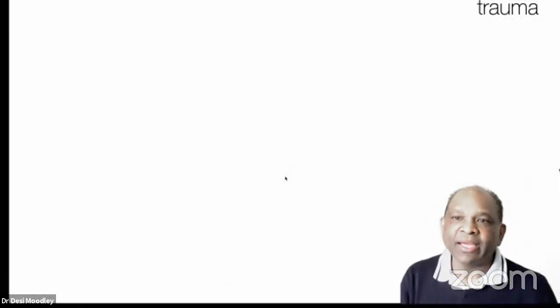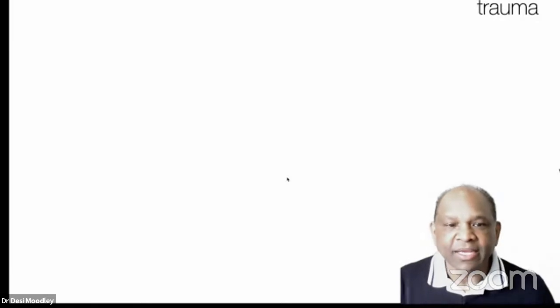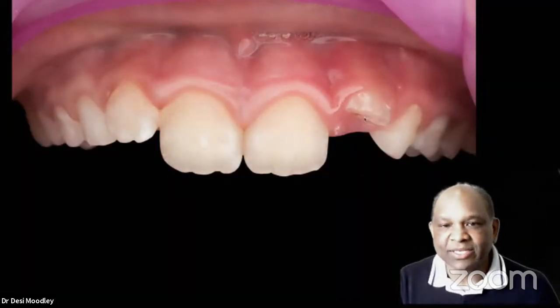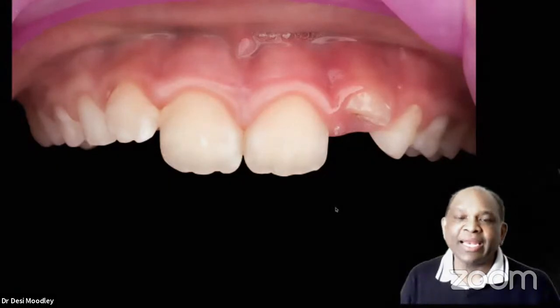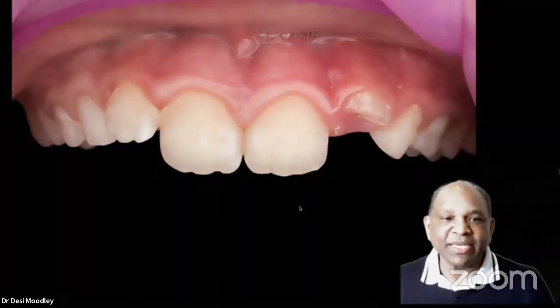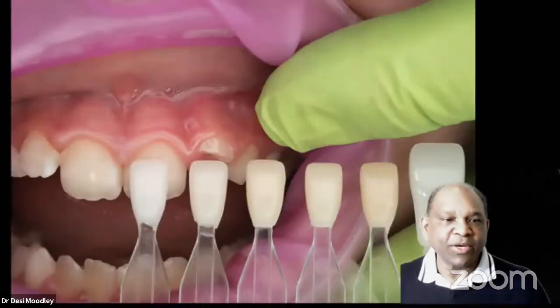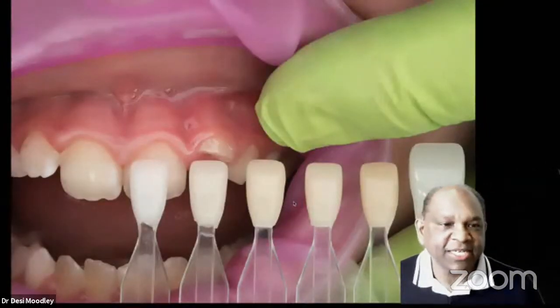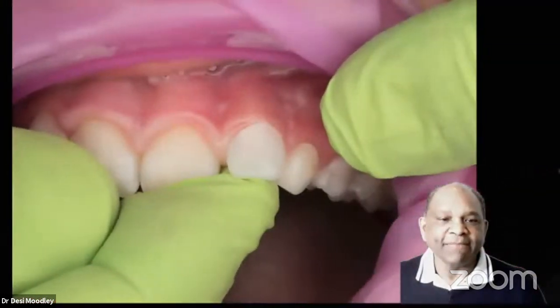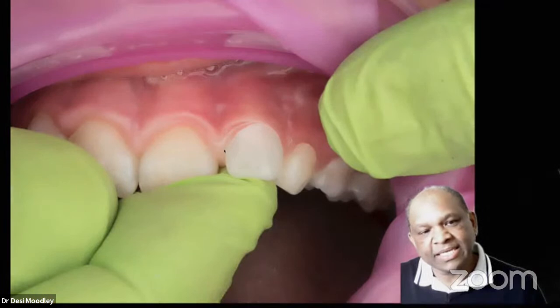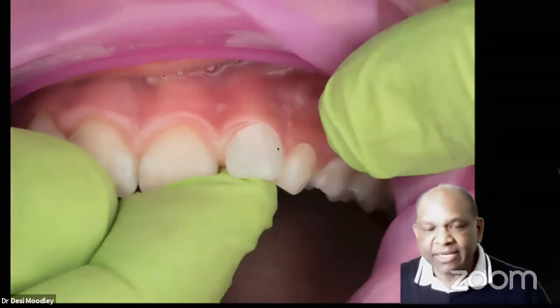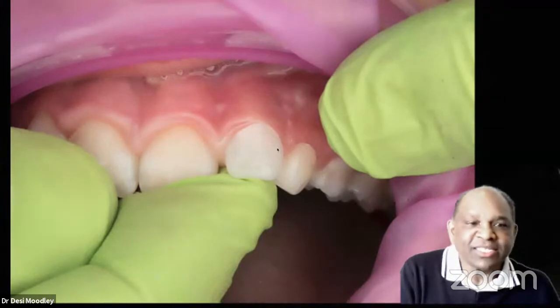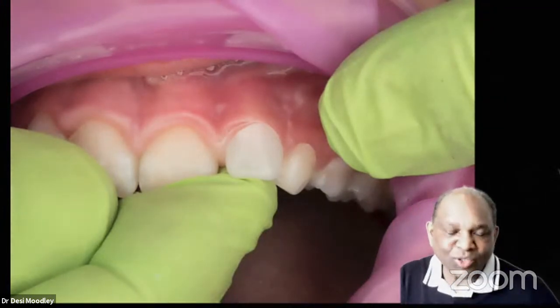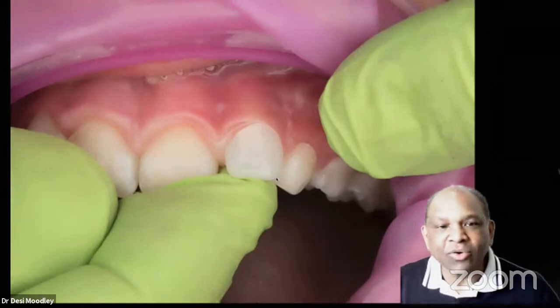The last case that I want to show you is a case that we did about 2 years ago. A child slipped at the side of the swimming pool and cracked the tooth. So she came in as an emergency, and we thought we'll place the Edelweiss pediatric crown. So this is what we did. Of course, we did a first color shade match, and then we adjusted incisally so that we could get a nice, good fit. And that's one of the big advantages. You can adjust the crown to whatever height you want to, so you don't have to cut or go subgingival.